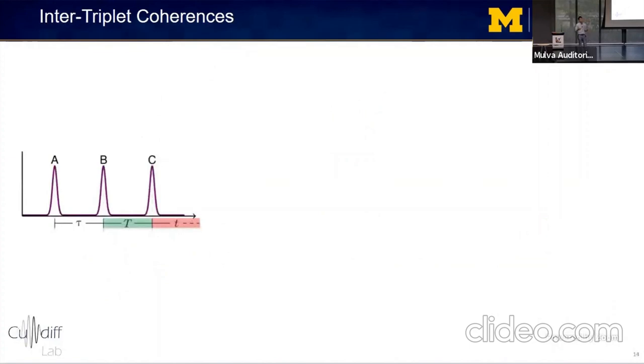So because we see signatures of optical triplet state coherences in our 2D spectra, we should in principle be able to generate as well as measure coherences between the triplet states as well. So these intertriplet coherences should show up as sidebands in what are called zero quantum spectra, which we measure by scanning the intermediate waiting time, capital T. So we first tried measuring zero quantum spectra with collinear excitation, but we didn't see any clear intertriplet coherences between states X and Y. This may be because the energy splitting was too small compared to the intraband dephasing rates, but we really don't know.